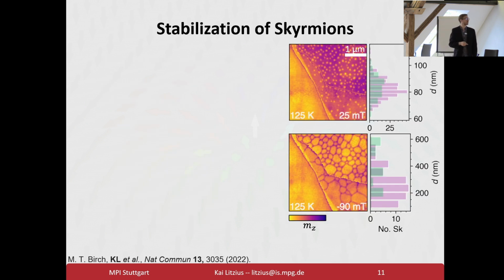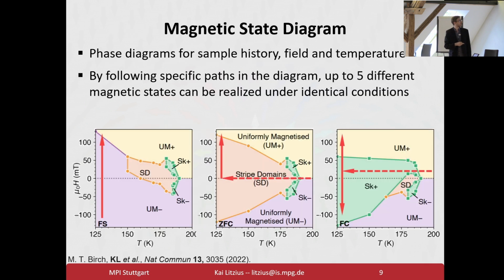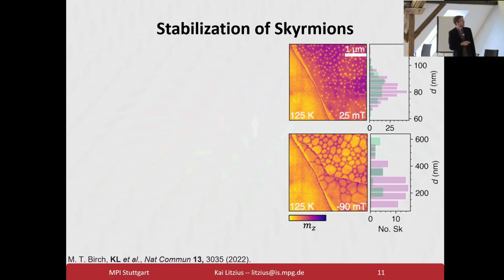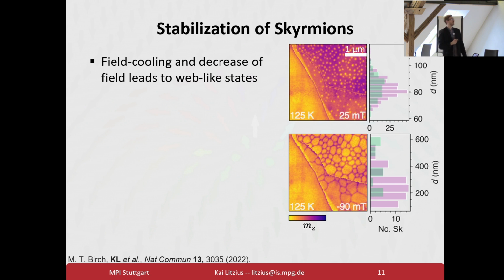The stability of these skyrmions is another question. And here, our results indicate that they're mostly dipolar stabilized, but they're still chiral. What do I mean by that? Well, we can do a field cycle, field cooling into a skyrmion array. This is essentially this state again. And then we change the field and expand the skyrmions in one direction. And we end up with these loose honeycomb-like lattices. These honeycomb-like lattices are something that you commonly see in systems that are dipolarly stabilized. So this is an indication that the skyrmions here have a significant dipolar stabilization component, where the dipolar interaction keeps them in the skyrmionic phase.